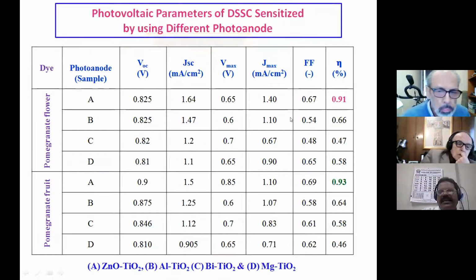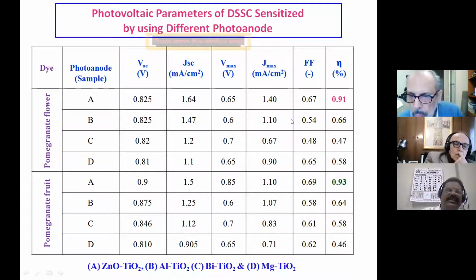The same thing we have carried out for different dyes which are naturally available in India, particularly in Tamil Nadu, in our area. So these are all the different cell types, and we have also changed the irradiance, that is how much light is falling on the surface: 48 watt per square meter, then 67, 115, 165. Like that, we have changed the intensity also. By having a 20-degree angle of incidence, 40 degrees, 60 degrees, 80 degrees, like that, we have moved. In this way, we look at the fill factor and efficiency.